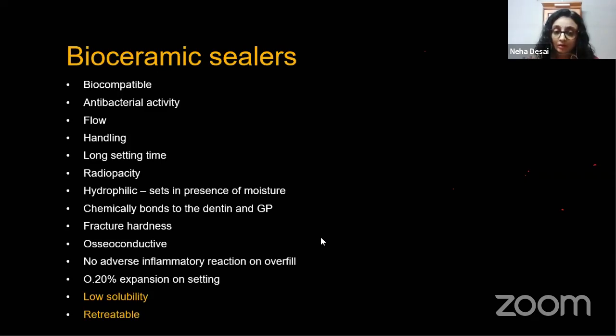It chemically bonds to the dentine and GP. It makes hydroxyapatite molecules at the interface. That is again a big advantage. The fracture hardness is high and it is osteoconductive. It does not have any adverse inflammatory reaction on the overfill. And it has slight expansion on setting, contrary to the other sealers, which have a tendency to shrink.